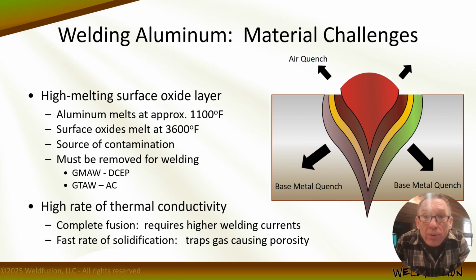At the same time, that oxide layer melts at a higher temperature than the base metal. Pure aluminum melts around 1100 degrees Fahrenheit, and oxides melt at about 3600 degrees Fahrenheit. So that's about 3 times higher. If you don't remove the oxide, it's hard to form a puddle and make a good weld.